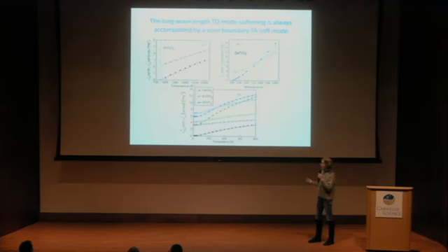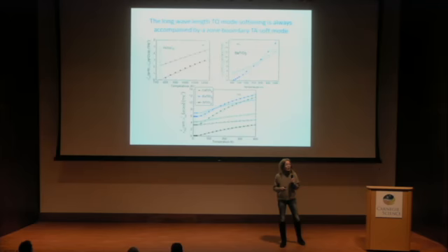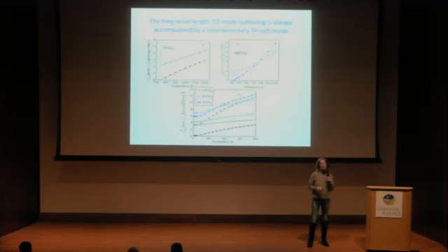So the first thing which we did is to calculate self-consistently the soft optic mode, which is common to all these 5 compounds. And what people easily and often overlook is that the soft optic mode is coupled to a soft transverse acoustic mode at the zone boundary.